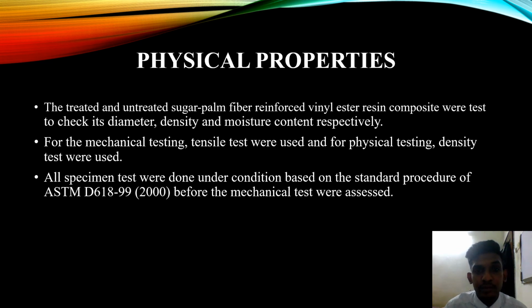The last physical property we measure is moisture content. The fiber was placed at room temperature of 27 to 29 degrees Celsius with 65% relative humidity of air for 24 hours before weighing. The samples were weighed as M0 before being immersed in fresh water for 24 hours at room temperature. After 24 hours of immersion, the samples were then weighed again.